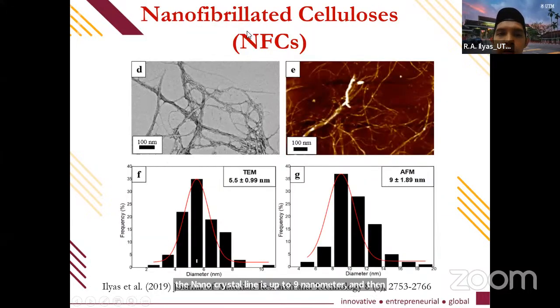So these are the TEM and the AFM figures of the nanocrystalline. It is rice-like, like basmati rice. We can see that the diameter of the nanocrystalline is up to 9 nanometer, and the length is up to 130 nanometer. For the nanofibrillated cellulose, because the length can be up to 10 micrometer, we only look at the diameter, which is 5.5 nanometer. This one is a bacterial nanocellulose, started from the bacteria.